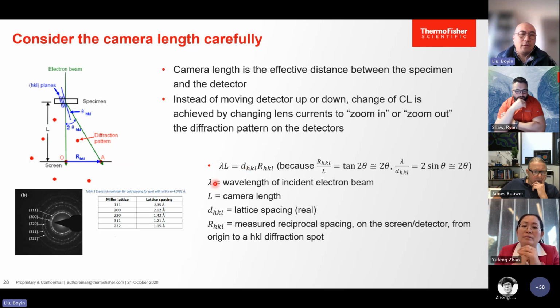So this is the equation for the camera distance. This is derived from the geometry between L and R, and then Bragg's law. Lambda is the wavelength of the incident electron beam. L is the camera length, which you really care about, and d_hkl is the real lattice spacing. It's a known value for your crystal, and R is the reciprocal spacing on the detector. This equation is also used for calibrating the camera length. We usually use a cross grating, which is polycrystalline gold, to calibrate the camera length using this equation.